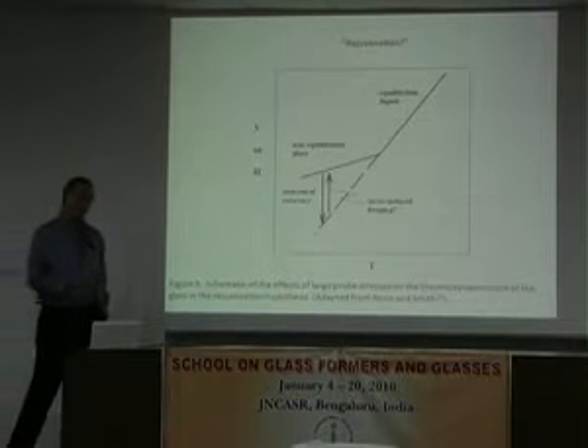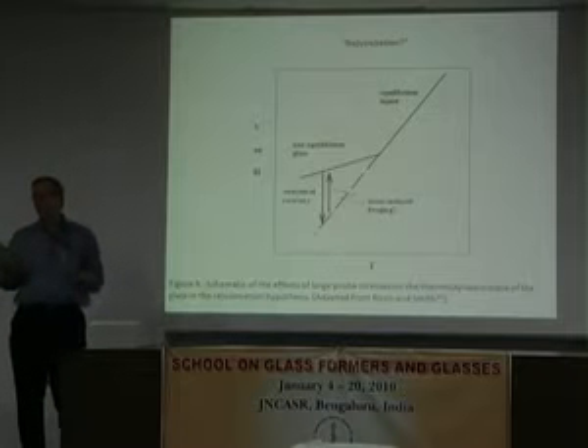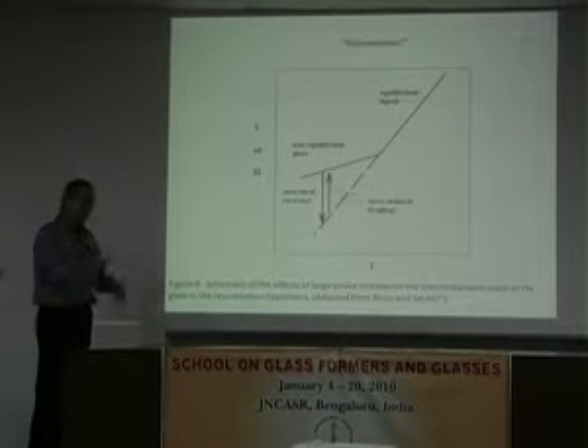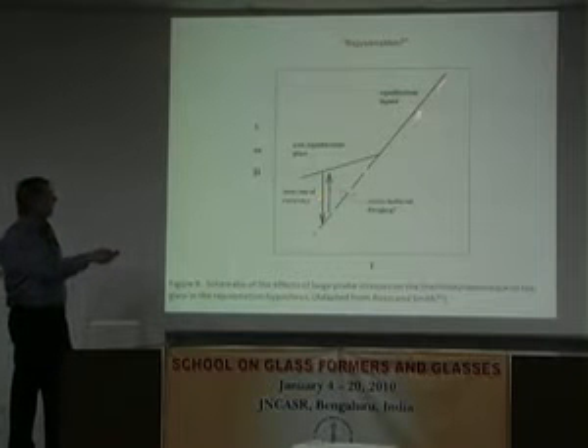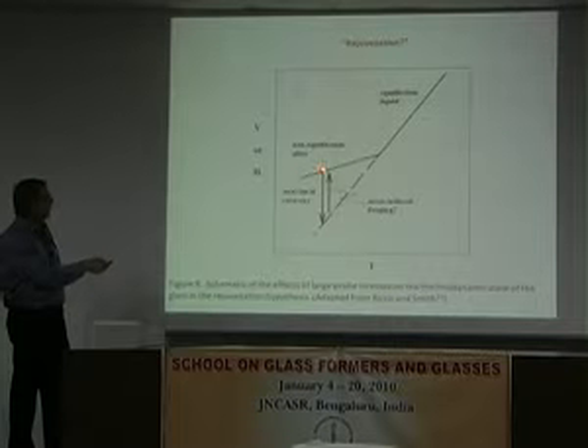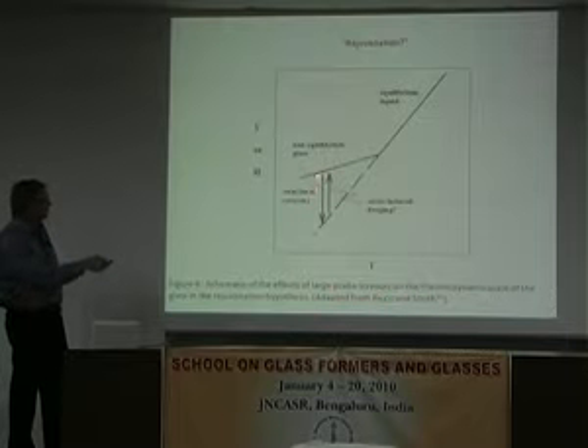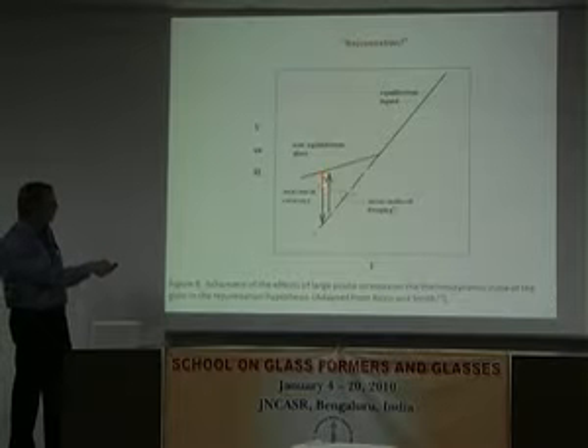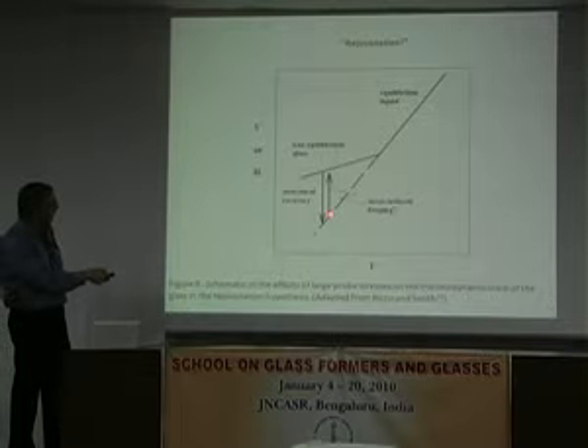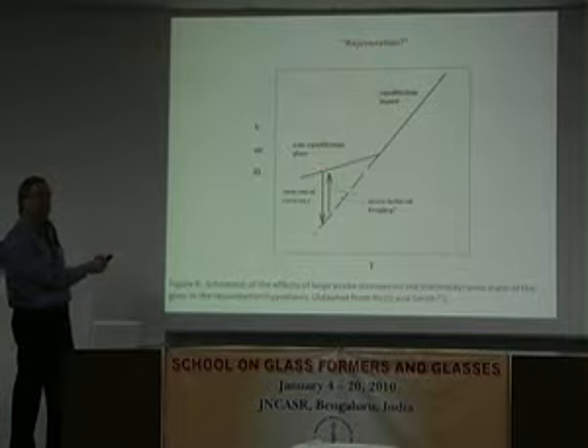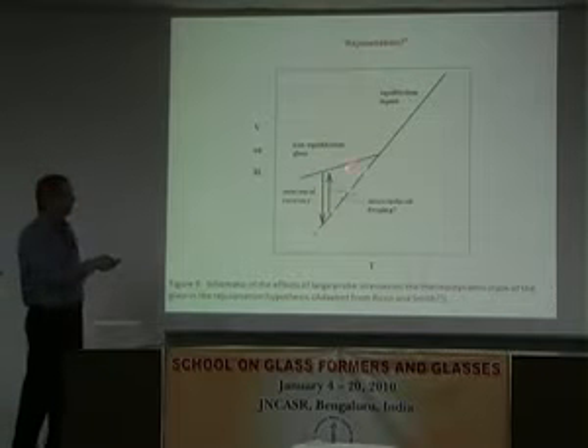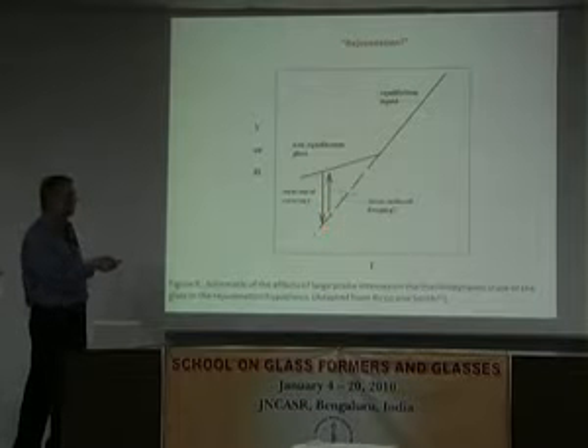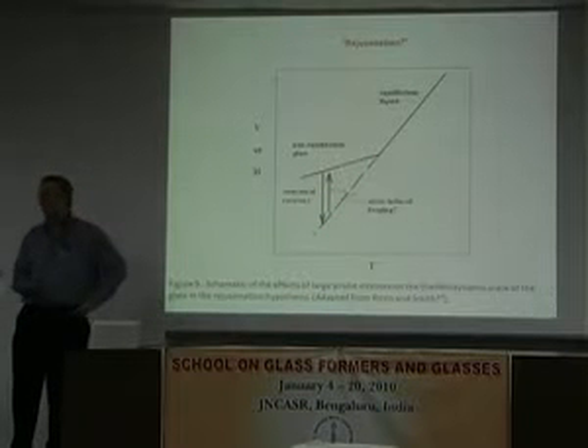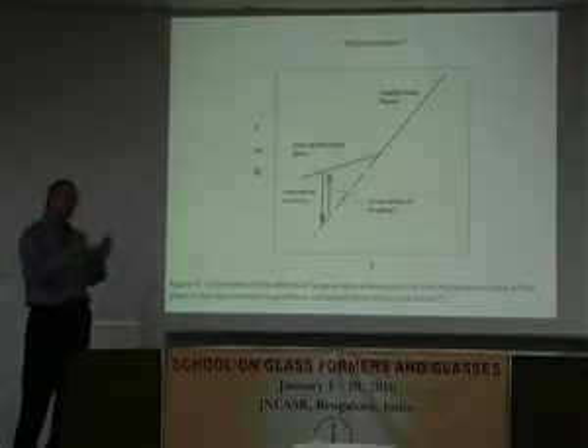Okay, so this is actually an important question, right? What are you doing to the glass when you put a mechanical deformation on it? And so here's what was stated, this is after Rico and Smith. What they said was, okay, I'm getting this physical aging or structural recovery going on, and when I put a stress on, I'm de-aging the sample right back up the same line. So I'm changing the structure of the glass as if I had just started the quench over again. So that was the original meaning that people put to rejuvenation.